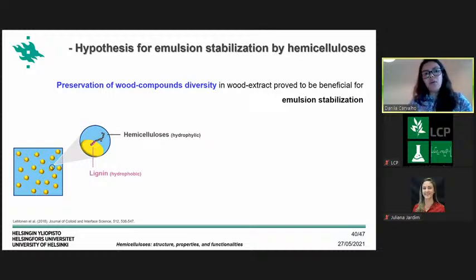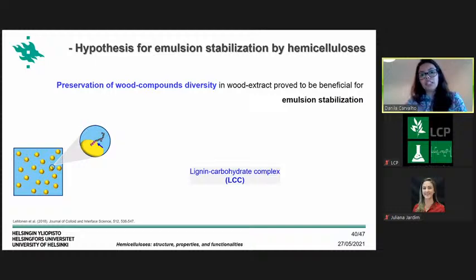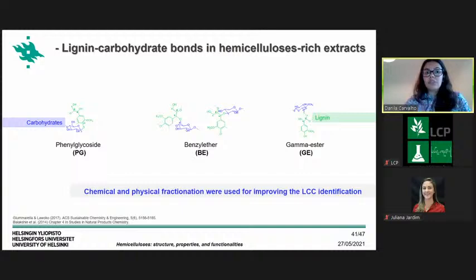But the question here is, how about the interaction between the hemicellulose and the lignin? What is the nature of this interaction? And the hypothesis was that the lignin and hemicellulose in this case are covalently linked by the so-called lignin carbohydrate complexes. In this hypothesis, the structure can explain well how this single molecule can have two different polarity sites that can interact with phases of different polarity. But at the moment when this hypothesis was raised, there was no chemical analysis or analytical proof of the existence of this LCC in the sample in the study. And this was when I could start to collaborate with this project.